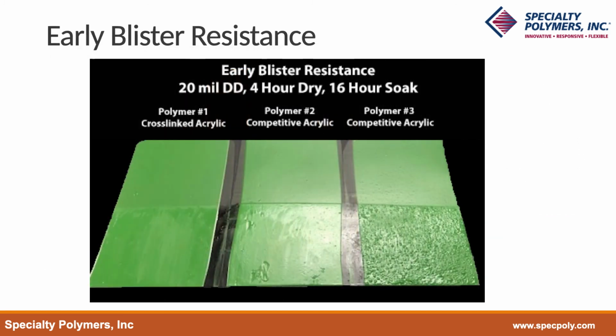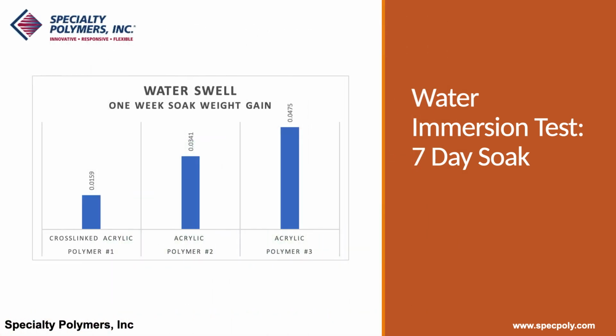This shows the early blister resistance of the three polymers after a 4-hour dry. The crosslinked acrylic was much better for early blister resistance. Even though we would not recommend applying these paints if rain is expected in a few hours, this indicates that the crosslinking would give better blister resistance, which might be due to a less water-sensitive film.